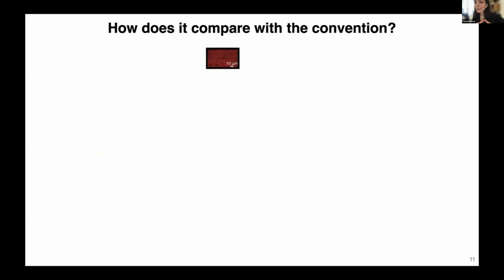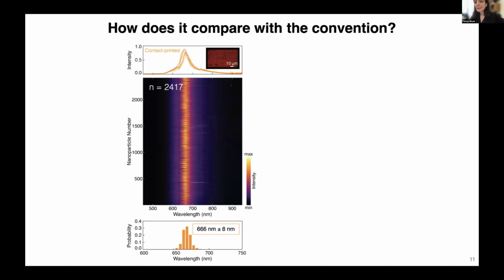It is also important for nanoscale devices that are made out of nanoparticles to have a uniform performance across an array of devices. So in this case, our approach allows us to create large arrays of devices. Over 2,000 devices were characterized through dark field scattering spectroscopy, and you can see the optical response is quite consistent.